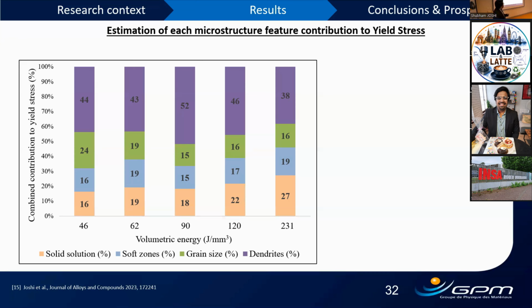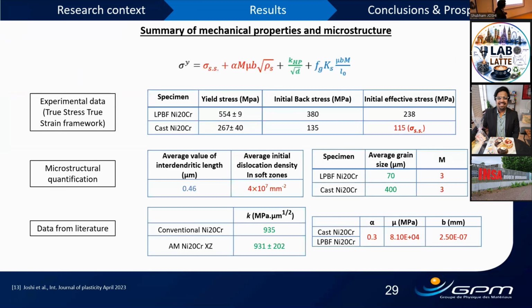Again, as I said, the most influential parameter is dendrites, and the error that we get for dendrites is quite small if we look at different locations. Moving on to different parameters, if we directly look at the formula, I feel dislocation density in soft zones could be a parameter which can be sensitive or which will change the model a bit. But we tried using different dislocation densities, so double or half the dislocation density that we have, and the effect is only, I think, 35 to 40 megapascal. So the error is not too much, and certainly we will have an influence of parameters like grain size and the dendrite size.